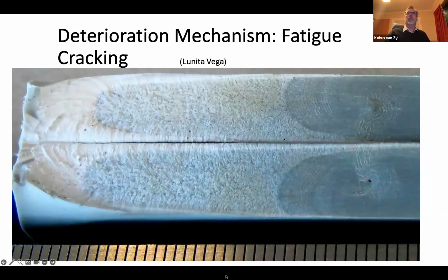The third deterioration mechanism is fatigue cracking, and this is a PVC pipe from the Netherlands that has a longitudinal crack, and you're seeing the inside of the crack walls. There's a weak inclusion there that created this, and what you can see there are these lines, and they indicate points where the crack length was. So the crack didn't happen all at once; it grew slowly over time until it was long enough to really break.